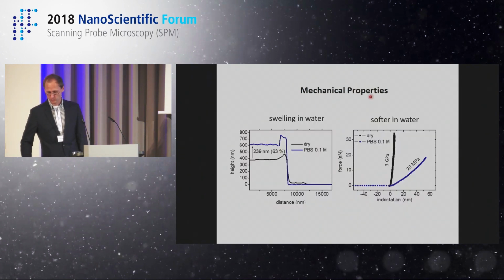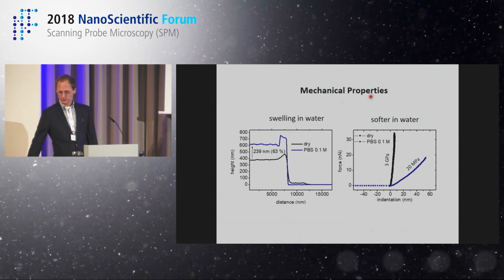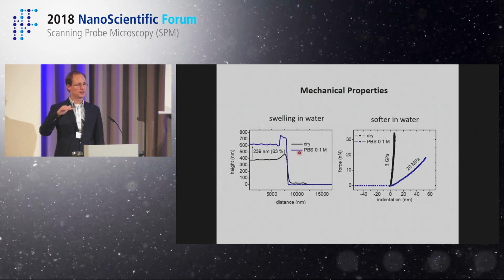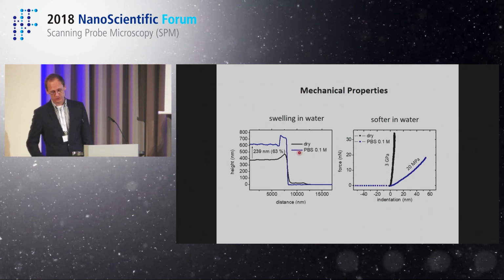We go further and we measure mechanical properties. First thing is that, of course, you have to realize, when you have such a film and you dry it in air and it's just dry, it behaves very differently than when you put it into liquid, because at the end, it's not a hydrogel, but it's, however, a material that swells, so it takes up water, that can also nicely be observed in AFM.